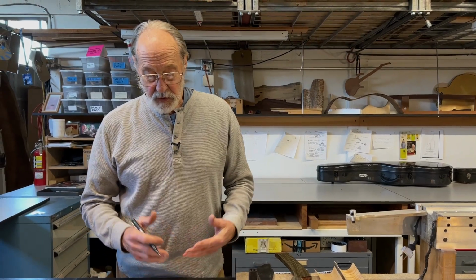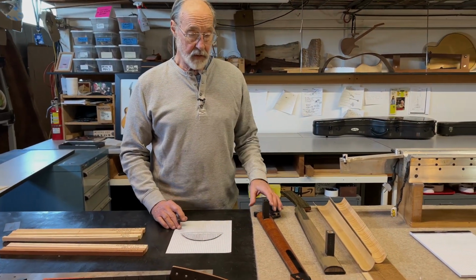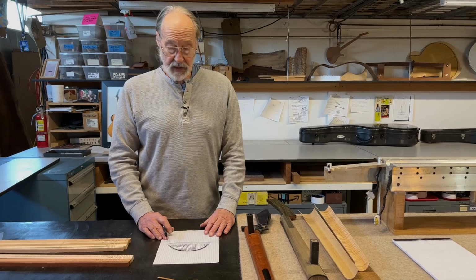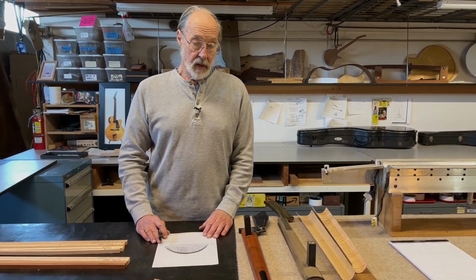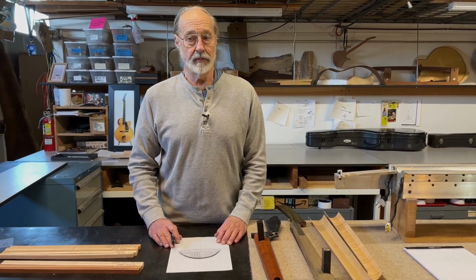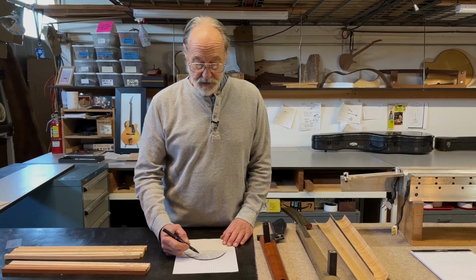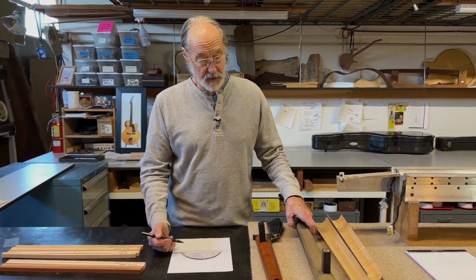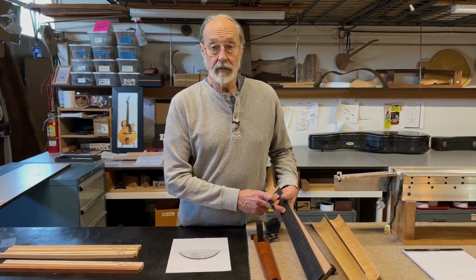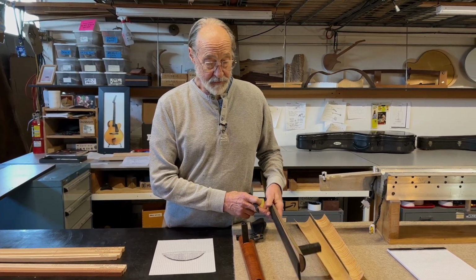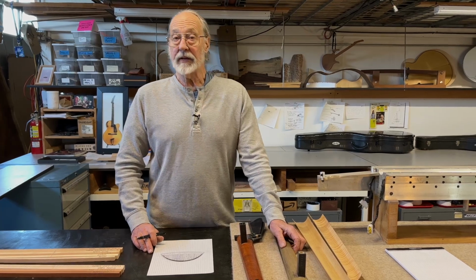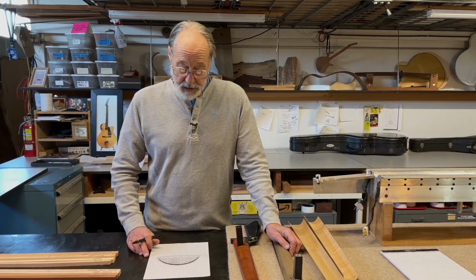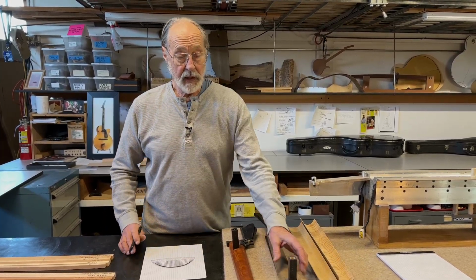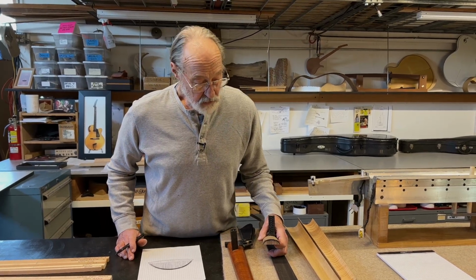The benefit of this is that we've created a structure that is very stiff and also very resistant to creep, because carbon fiber and a good, strong epoxy resin together in that composite configuration, carbon epoxy, is almost completely impervious to creep and has a beautiful memory. This is great. It means that we can choose the materials that we want to use for their suitability to the purpose at hand. For the fretboard, it would be resistance to being worn out and a nice slippery feel for the player. And for the back of the neck, it would be an attractive material that would feel good, again, feel good to the player. And then in the center, a reasonably lightweight material that sounds good and also doesn't weigh too much.